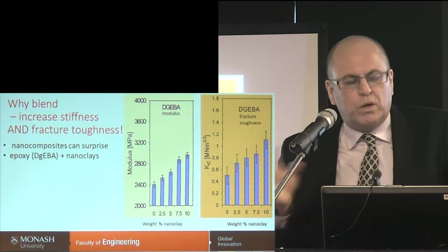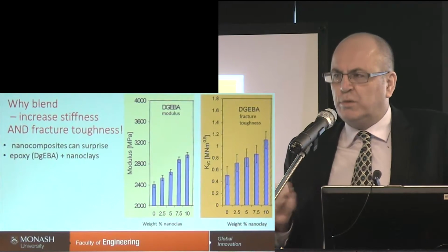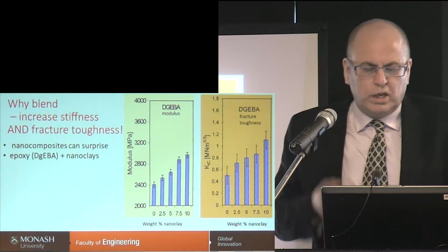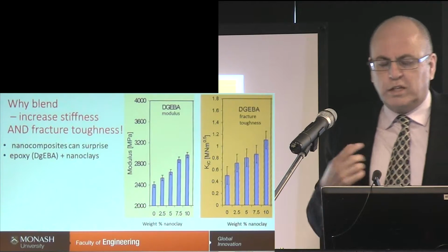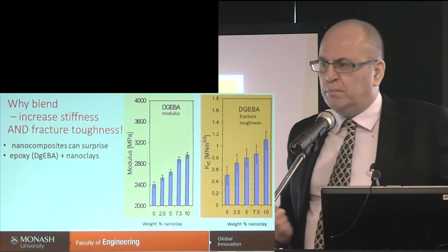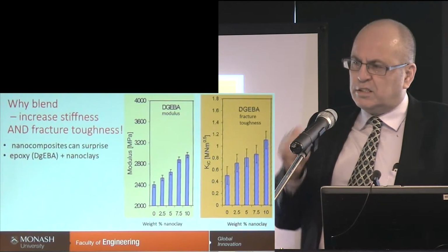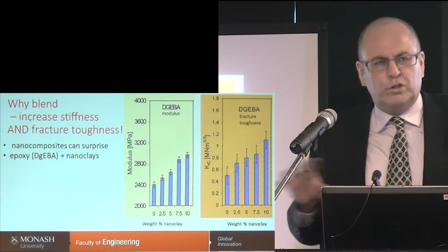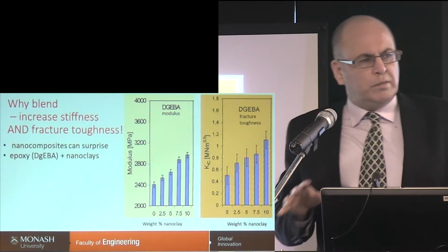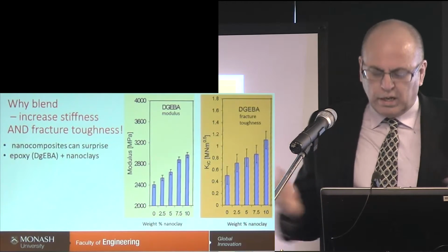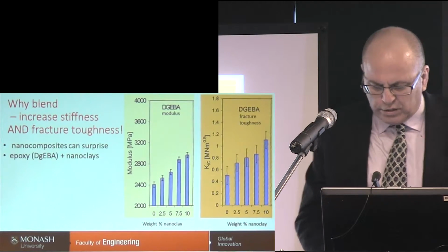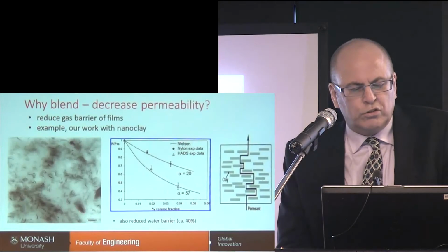Here's just an example, by the way, where we use nanoclay in epoxy resin, DGEBA, the commonest epoxy resin. We found we could get a substantial increase in modulus, and at the same time we could get an increase in fracture toughness. That's a paradigm that's rarely found in materials engineering, because normally you make something more rigid, it becomes more brittle. But because of the surface areas and other factors, you can actually introduce good properties.